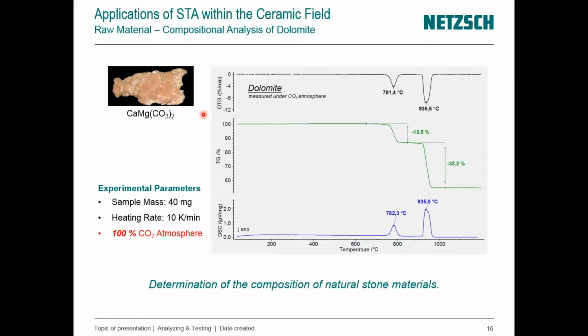And this is because we talk here about equilibrium reactions. So we can influence the reaction, especially the second reaction here, by the released gases of the first reaction. This comes because we use here special lids and everything. So we just mimic that there are 3 steps. This is not good in principle because we want to know really the composition of the calcium magnesium carbonate directly.